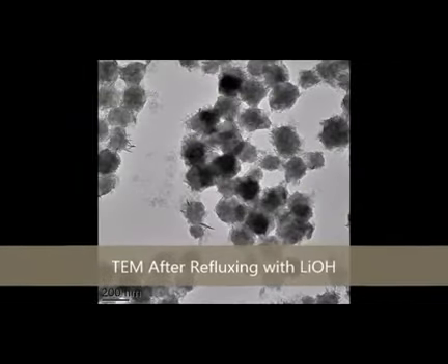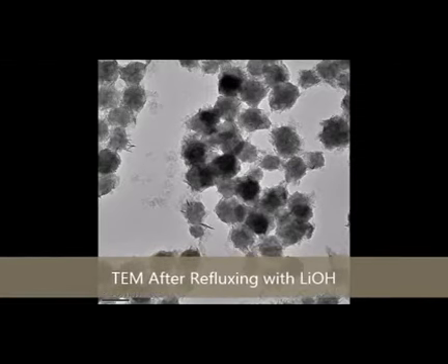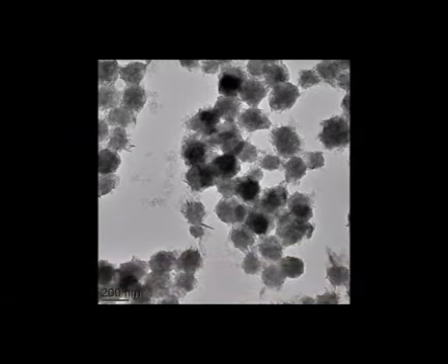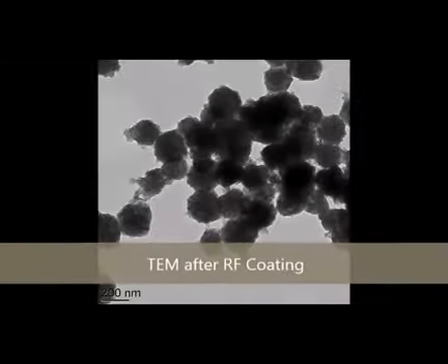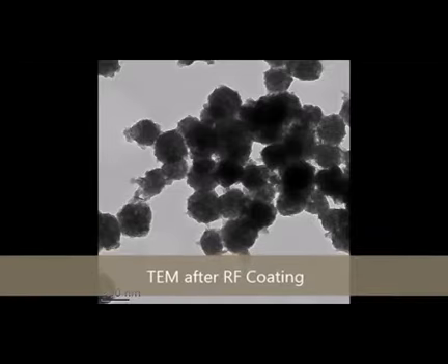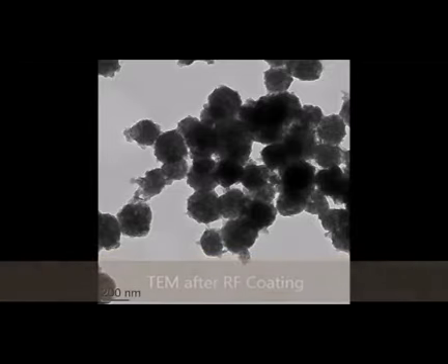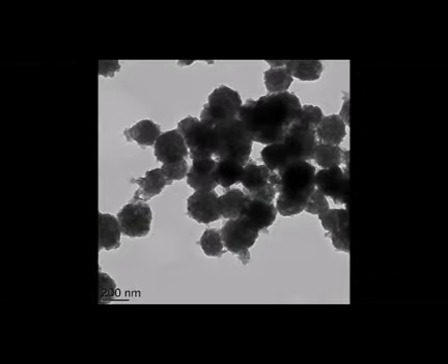Here we have a TEM image of lithium titanate particles after refluxing with lithium hydroxide. The TEM image shows the porous, flaky structure which is a common feature of hydrothermal titanate production. Here we have a TEM image after coating the lithium titanate with resorcinol and formaldehyde. The TEM image shows how the particles smooth out after the coating.